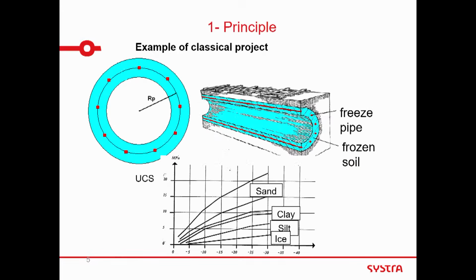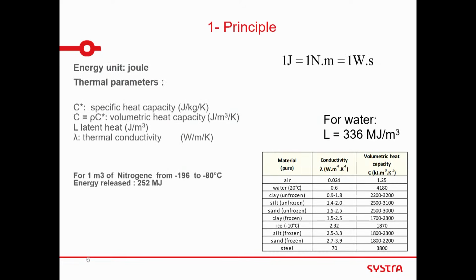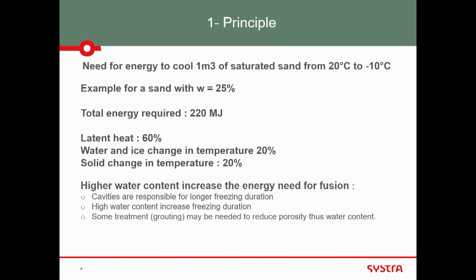What is very important, in fact, is this: the energy to freeze the soil depends on the latent heat of transforming water to ice, around 0 degrees. It's a lot of energy. And how much is it in the real case? If you take 1 cubic meter of saturated sand, initial temperature is 20 degrees. Final temperature is -10. I will explain to you slightly later on why I'm choosing -10 degrees. With water content of 25%, so the porosity is 40-something percent, 45% if I remember well. The total energy required is 220 megajoules.